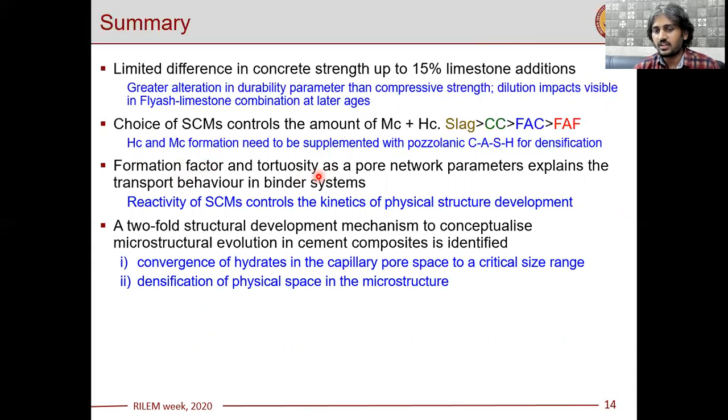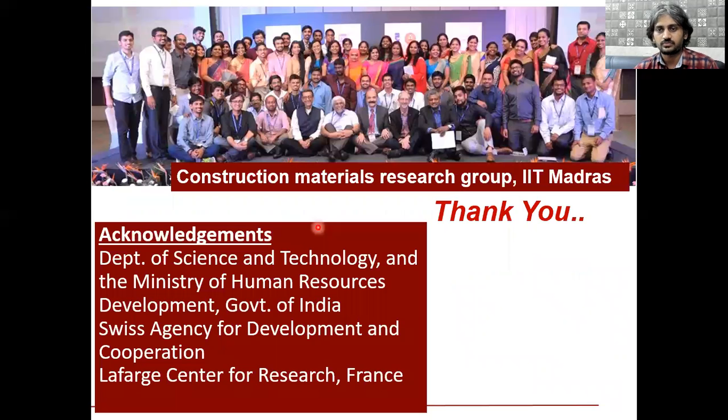It is seen that the reactivity of the SCM primarily governs the kinetics of the physical structure development, and based on the trends of formation factor versus pore size, we identify a twofold structure development mechanism, where there is initial convergence of hydrates in the capillary pore space to a critical size range. Once the critical size range is reached, there is densification of the physical space in the microstructure.